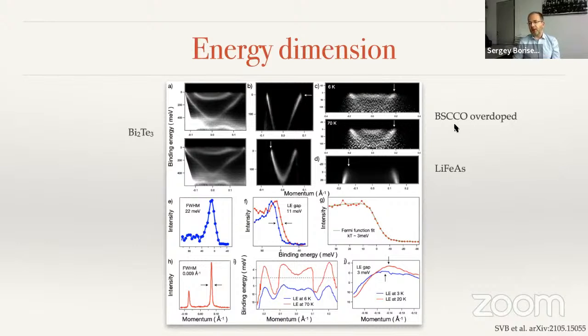For instance, in overdoped Bi2212 single crystals, you could see the opening of the superconducting gap of the order of 11 meV. You can track the shift of the leading edge, even in lithium iron arsenide, where the superconducting gaps are an order of magnitude smaller. So this instrument is now available.